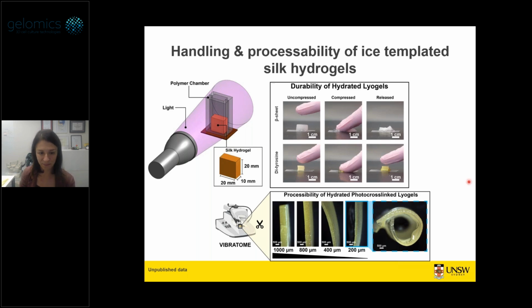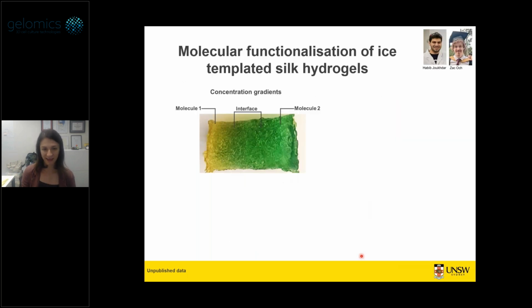They recoil really nicely. And because they're so easy to handle, it means that we can start processing them using standard processing techniques, including cutting them with the vibratome without the need to embed them or process them in any way. So we can cut them down to 200 and I think now even 100 micron thick, so that we can implant them or use them to grow cells on and so on. But as I said, to me, the coolest thing about these is that we can now start introducing concentration gradients into these very large structures. So this is now a nicely templated silk hydrogel where we've introduced two different molecules, and you can see you can get molecular gradients and these interfaces in the materials. And these are now trapped in there, which we could not do with our solutions.